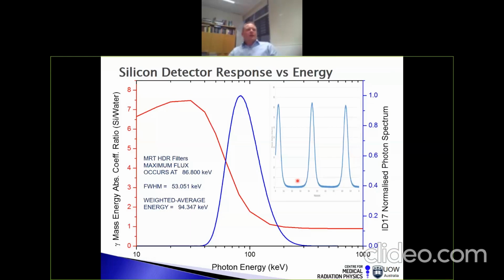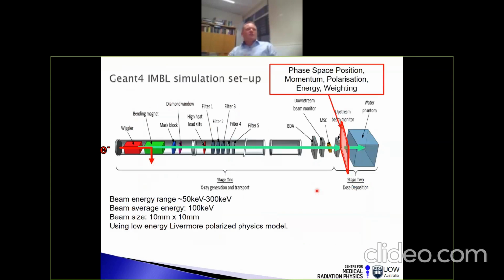Now, the problem is, of course, this is our energy spectrum in blue, and the energy spectrum is sitting right here, looking at the mass energy absorption coefficient ratio of silicon compared to water, and you can see it's a very challenging environment. Because if we have any change in the spectrum between our peak and our valley region, in our photon spectrum, we're going to get a different response in our silicon. So that has huge implications for the dosimetry, and it's very, very complex and something we spend a lot of time on. This is where our simulations come into play, so Monte Carlo simulations.